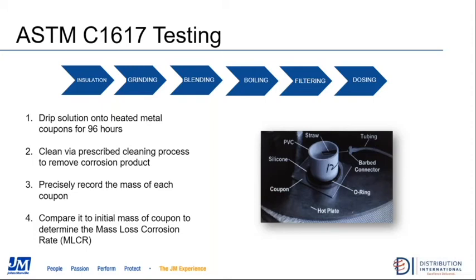At that point, the solids remaining are separated from the solution, and then that liquid is dripped onto the surface of the coupon via the mechanism shown in the picture, and that is done for a period of 96 hours. The temperature of this is such that as the liquid drips onto the coupon, it very rapidly boils away, so replicating those real-world conditions of water getting into the insulation system but being evaporated off by high process temperatures, and then that process repeating over and over and over again. At the end of the 96 hours, the mass of the coupon is measured again, and then the initial mass and the final mass are compared, and a mass loss corrosion rate, or MLCR, is calculated for that individual material.